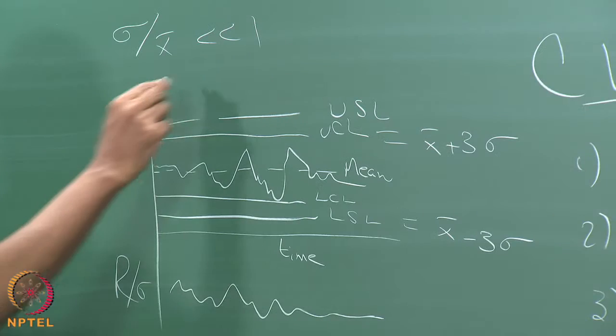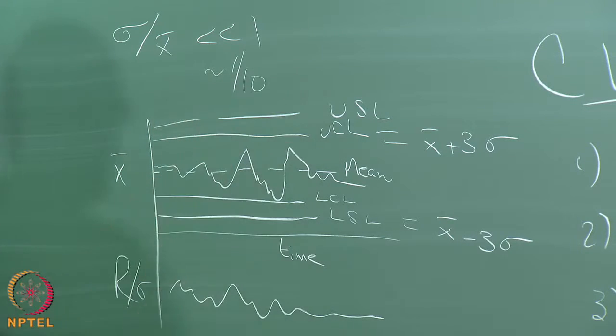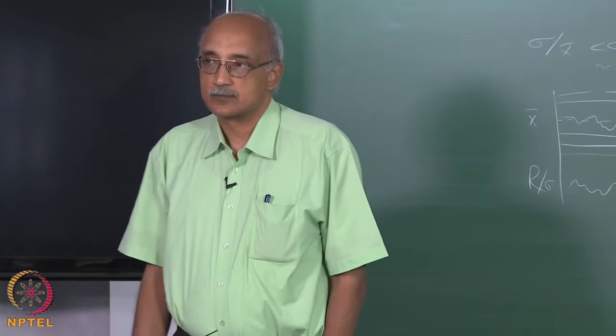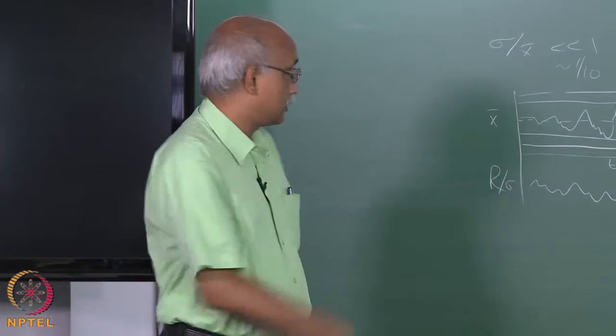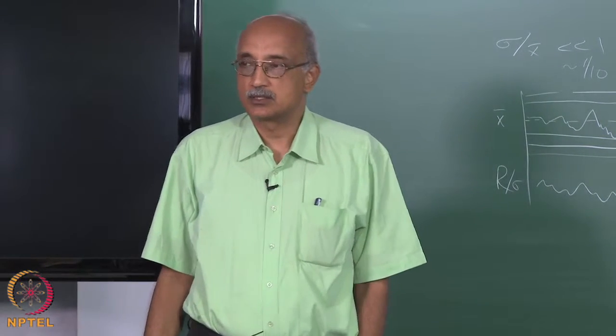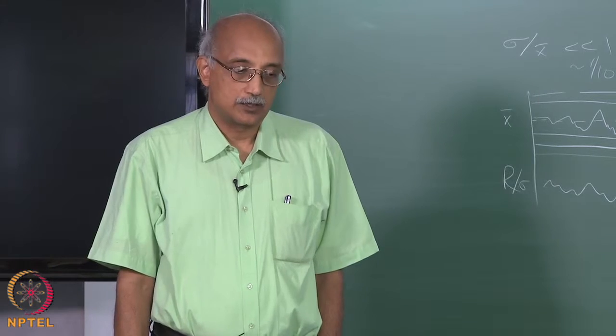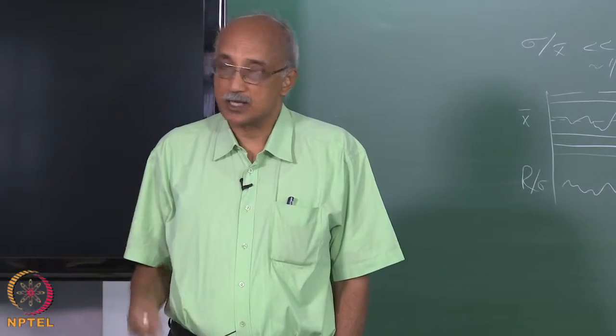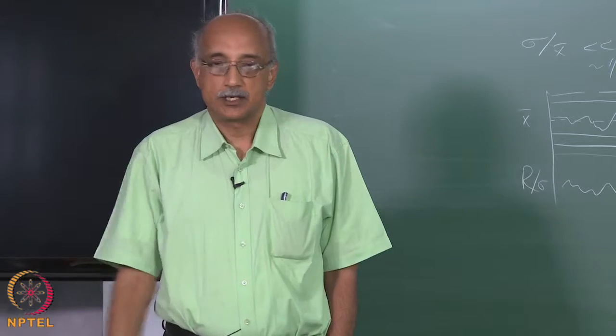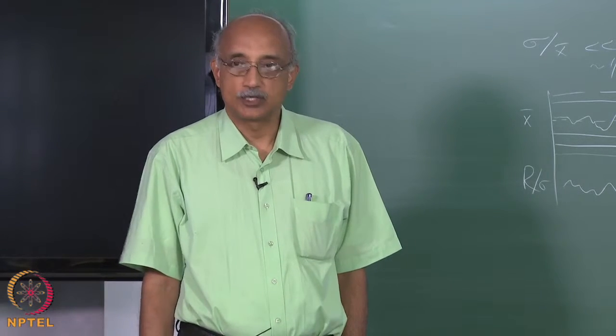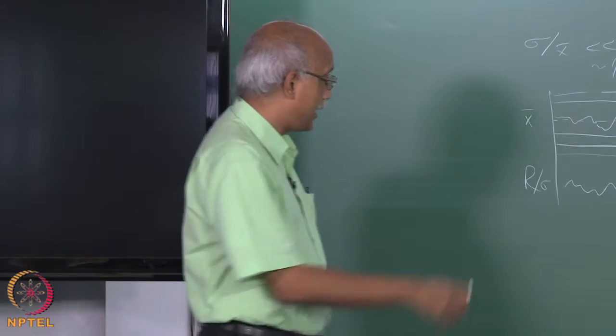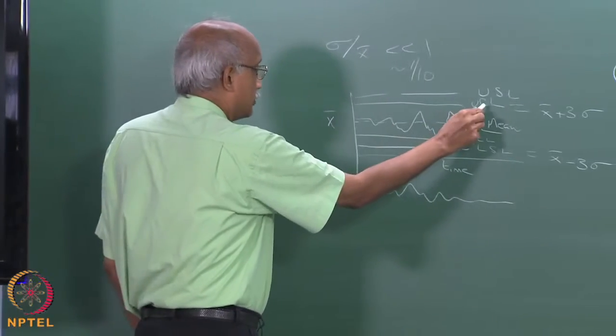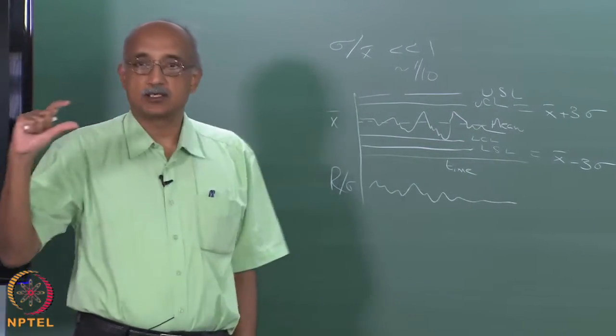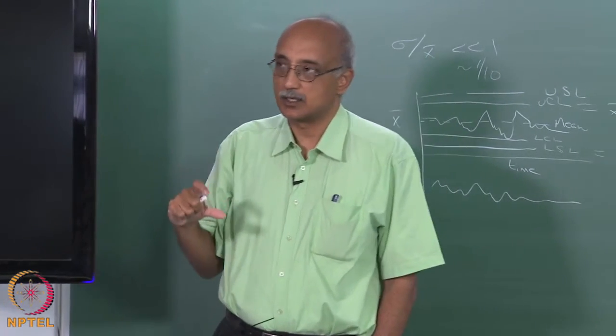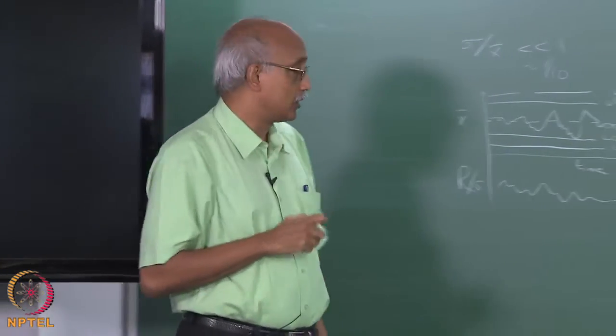And in fact, typically in a well-behaved process, the ratio of standard deviation to mean should not exceed 1/10. Okay? This parameter is called the variability coefficient. In a good, robust process that is running under well-controlled conditions, that ratio should never exceed 0.1 or 10%. If you do that, then obviously your UCL and LCL are going to be much tighter than the corresponding USL and LSL, and that's what you're aspiring for.